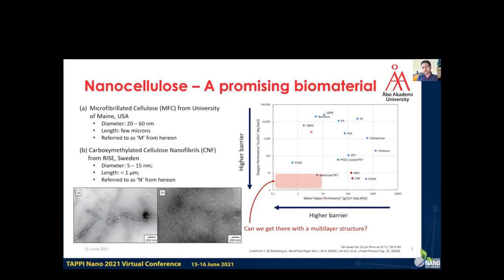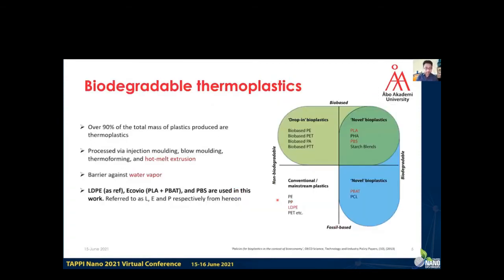And common polymers such as HDPE and LDPE that are used in packaging have good water vapor barrier, but rather high oxygen permeance. So the target here is to get as close to this red box as possible, which has both low oxygen and water vapor permeances, or good barrier properties. So the question is, can we get there with a multi-layer structure while keeping it biodegradable?